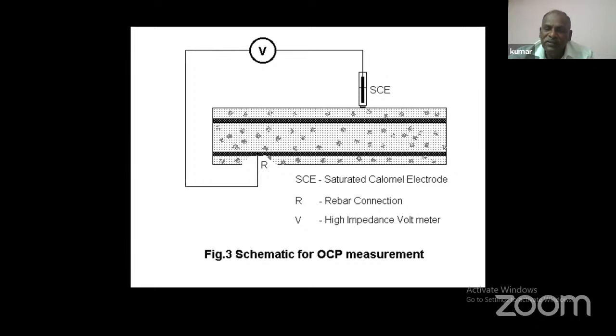So you need one reference cell, and another one connected to the reinforcement rod. And you have to have a high impedance voltmeter to measure the potentials. I said already, potentials means in the potential-pH diagram, with respect to different pH, steel exhibits a certain electrochemical potential. So on the surface of the concrete, we find the electrochemical potential is not constant. It varies depending upon the different contamination of the concrete surface. If more chloride is there, then correspondingly you will get a more negative open circuit potential.